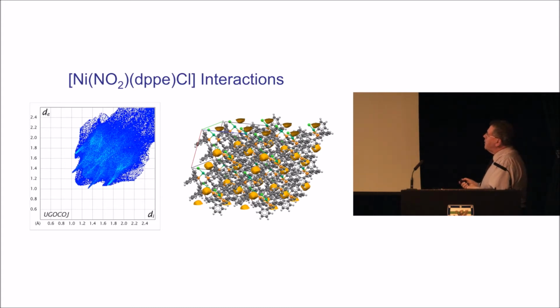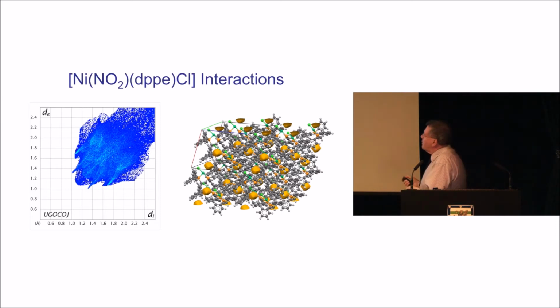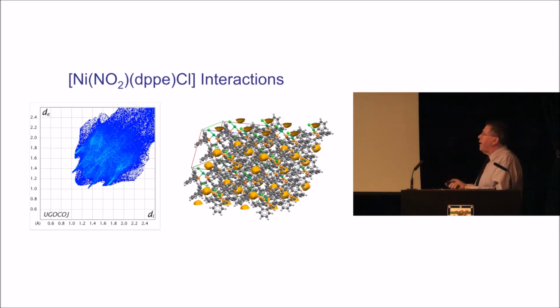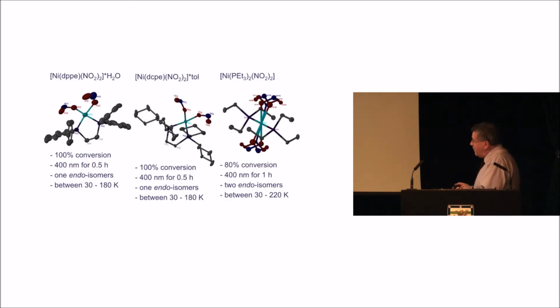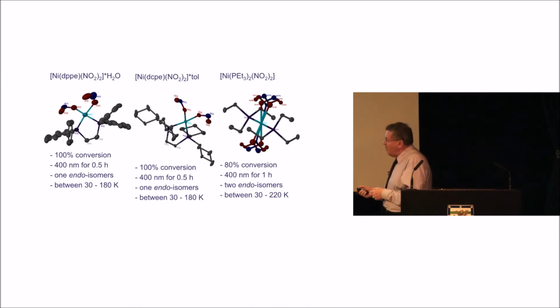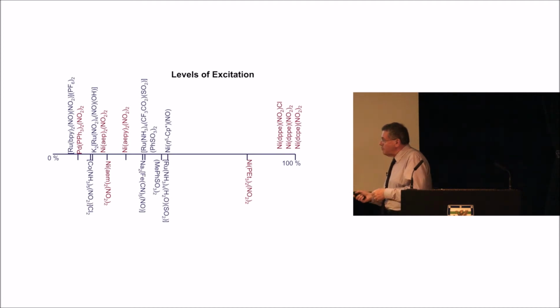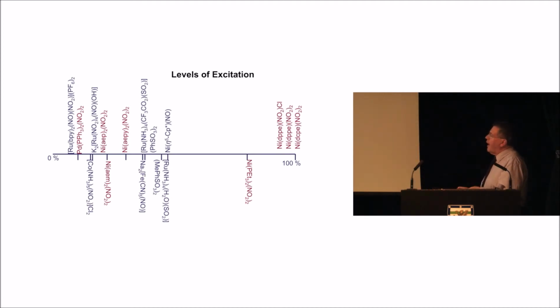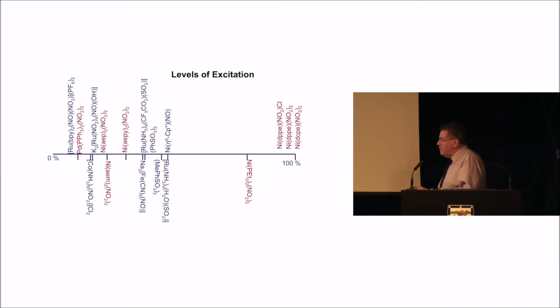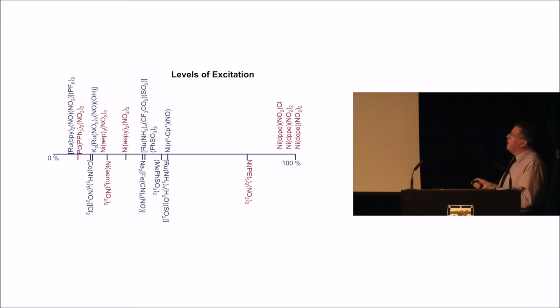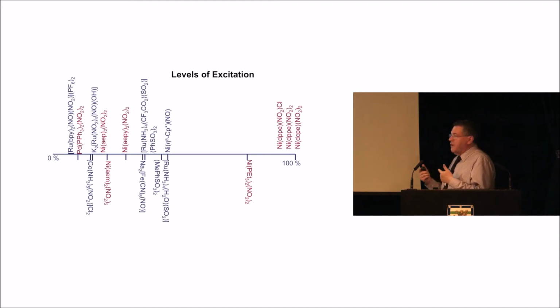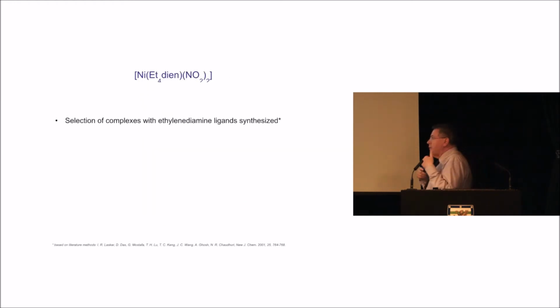But if you take the NO2 out and recompute the structure with the cavity space, you can see that we have these reaction cavities that are big enough for the NO2 to rearrange. So that works fine. And spurred on by this success, you can do this from a number of similar complexes, with slightly different conditions, but we now actually have a series of these. These two molecules both go to 100%. This one goes to 80% conversion. So we've achieved one aim of getting systems that can switch reversibly 100%. So can we do more than this?